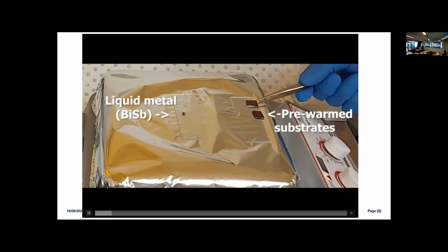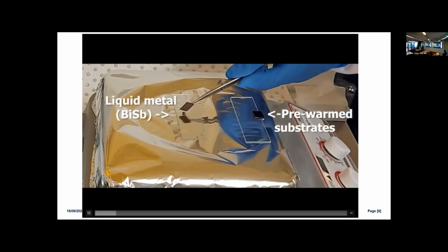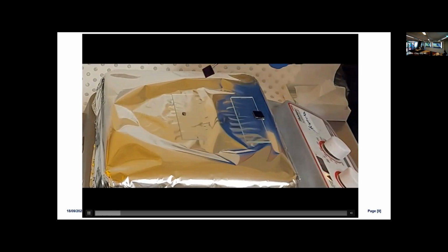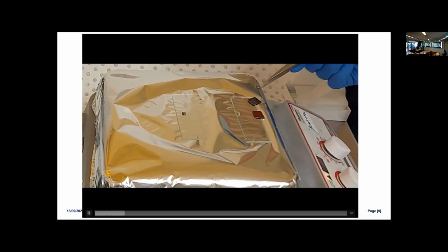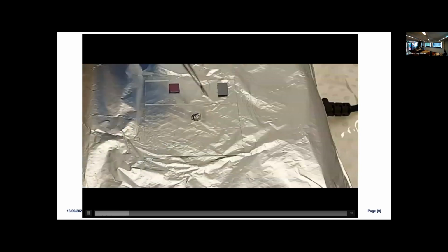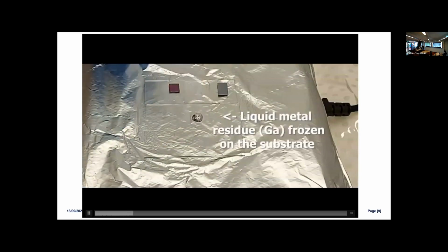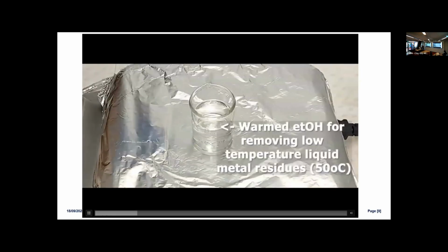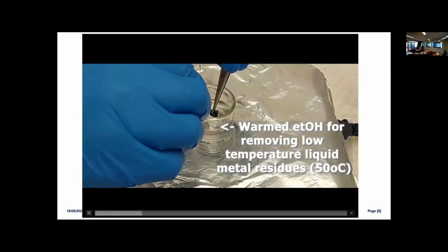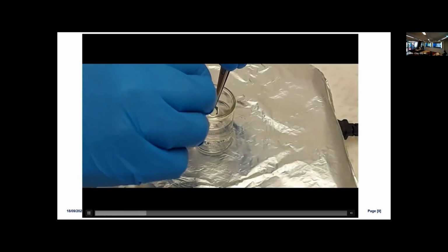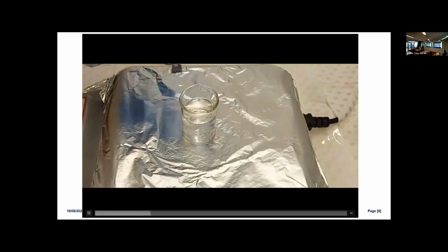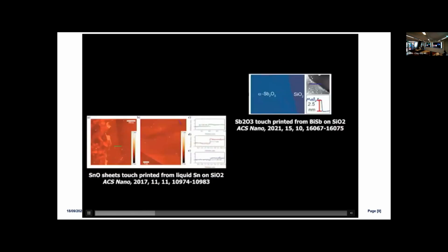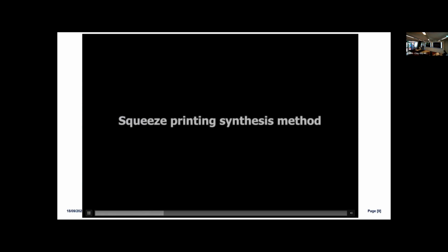Firstly, touch printing. You can grab a substrate and touch it to a liquid metal, and then you've got a 2D material printed, as simple as that. Or you can basically squeeze, and then you get a larger area. But because you delaminate, the liquid metal can also be wiped off in warm ethanol, so it can be easily cleaned.